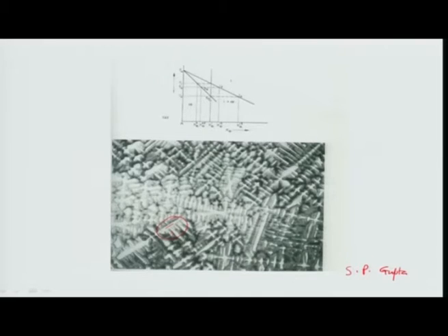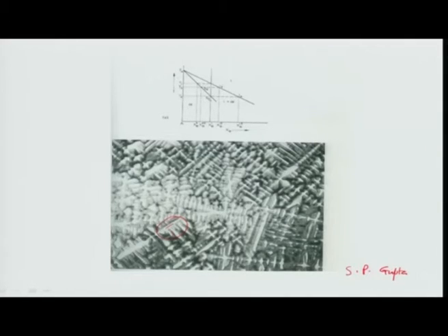Normally we prepare samples metallographically by using certain polishing and then followed by etching. Etching means using certain kinds of chemical agents to remove certain things in the microstructure. Like in copper nickel alloy, you use ferric chloride as the agent. So what will it do? Ferric chloride will react with copper and remove the regions where copper is present. And if I remove those regions, the regions will form microdents, and therefore in optical microscopy they will look dark.